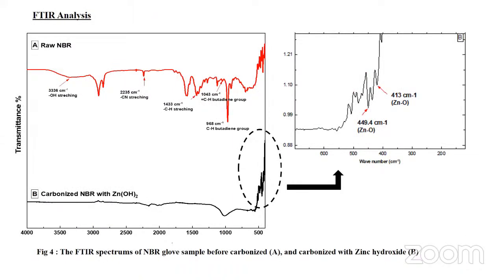In the FTIR analysis, we can clearly see all the characteristic peaks related to the raw NBR sample have disappeared after the carbonization of the sample with zinc hydroxide. Two dominant peaks related to the interatomic vibrational mode of zinc oxide can be observed in the fingerprint region of the carbonized sample. This further confirms the successful conversion of zinc hydroxide into zinc oxide.